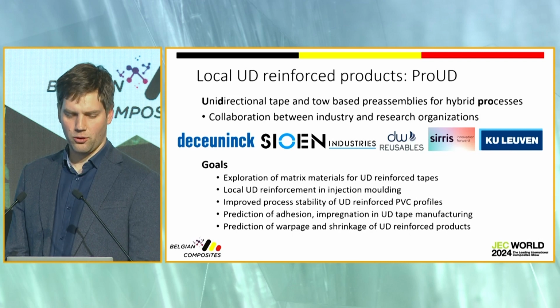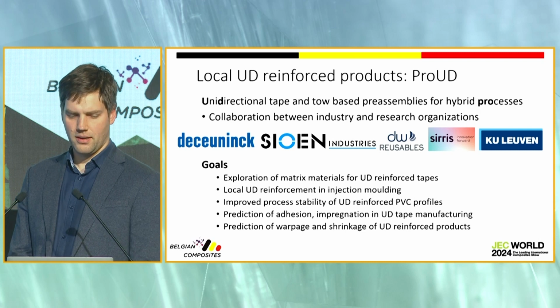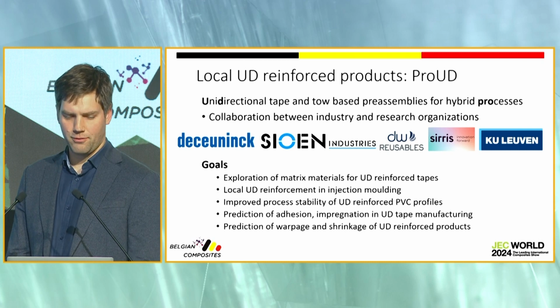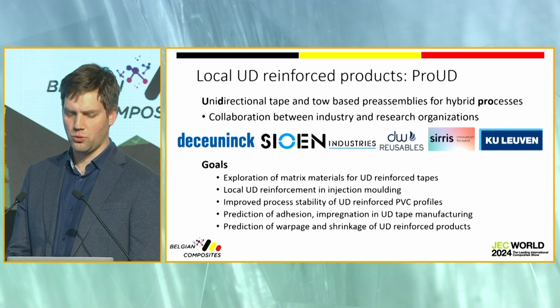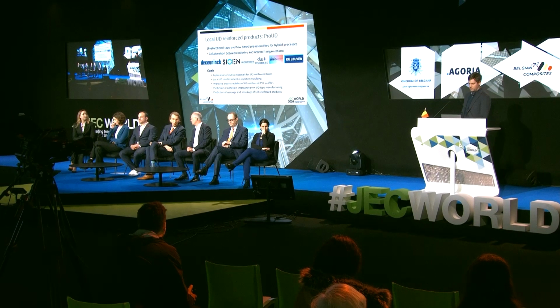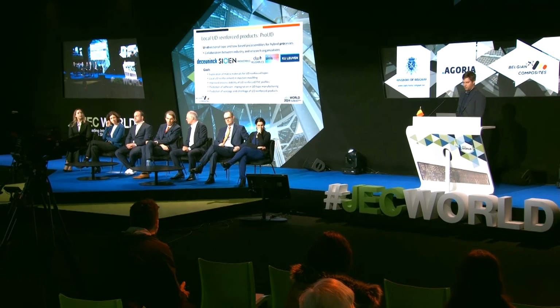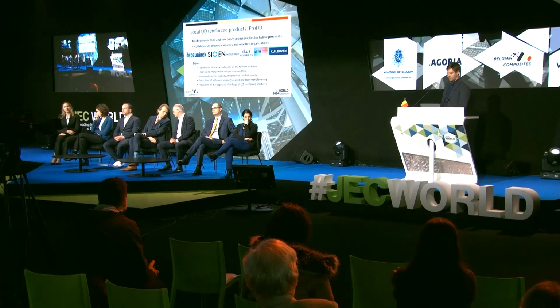Next to that, we also want to have the quality, of course, and that is why we need the prediction of the adhesion between the UD tape and the thermoplastic PVC, which is the rest of the profile. On the other hand, it's also important that we have a good impregnation of the UD tape during the manufacturing, so that we have a good and stiff product at the end.